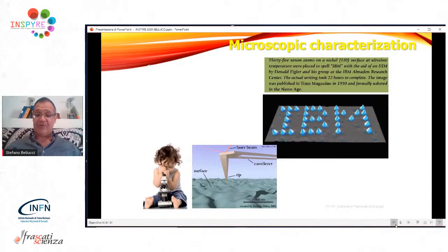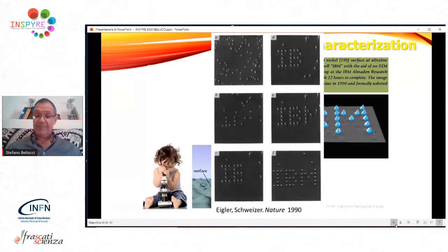You see another type of microscope that is an atomic force microscope, briefly AFM, which scans the surface of a film and identifies the roughness, the highs and lows on the surface by using a laser beam that hits a cantilever equipped with a tip. This tip is scanning in different modes, tapping, contact, non-contact, and it can give us the very tiny features of the surface up to the atomic layer with atomic level precision.